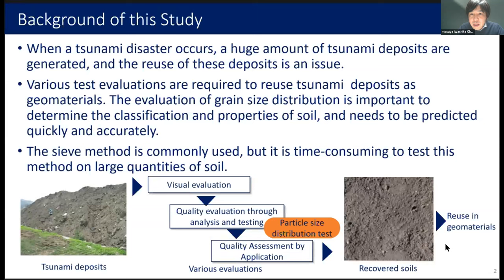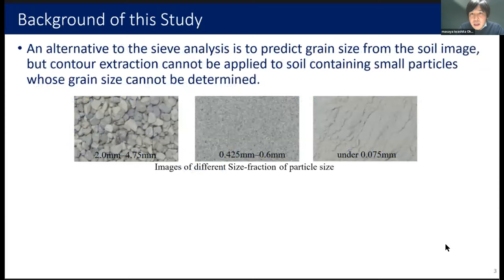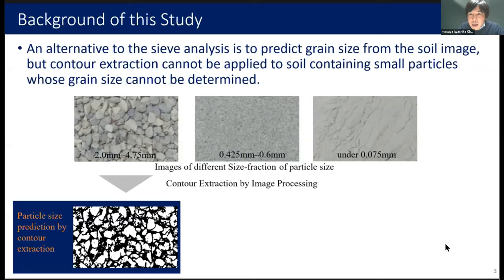But sieve analysis to predict particle size distribution cannot be performed on large quantity of tsunami deposit. An alternative to the sieve analysis is to predict size by extracting grain contour from the image. However, this method cannot be used for small particles whose size cannot be identified from the image. The photos shown here are close-up views of soil samples of different particle size taken with a standard digital camera. Soils in the particle size range 2 mm to 4.75 mm had their contours extracted by image processing.